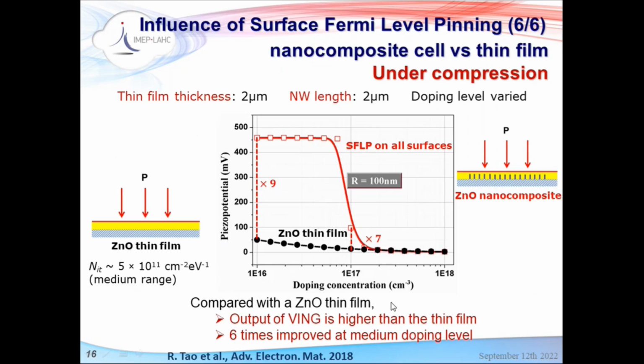Now, if we compare again the thin film, which includes surface traps as well, and the composite, including surface traps and doping, you can see the comparison in this curve. So this is the potential, again, as a function of the doping concentration, and the black curve is the zinc oxide thin film, and the red one is the composite. So you can see that in this range of doping concentration, the nanocomposite could outperform, again, the thin film. And all of this is for the same thickness of 2 microns.